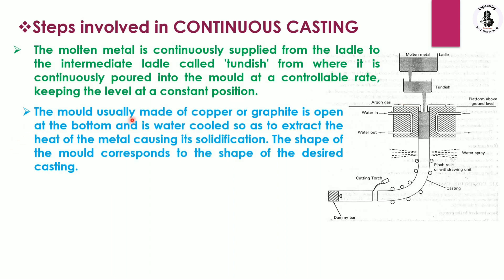The mold, usually made of copper or graphite, is open at the bottom and water-cooled so as to extract heat from the metal, causing its solidification. The argon gas as well as water in and water out control the temperature and help with solidification of the molten metal, producing a continuous solidified product.